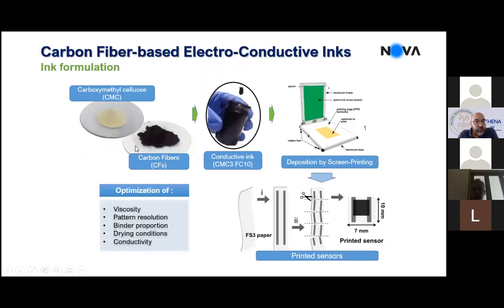And so we made this conductive ink that is a mixture of carbon fibers with a cellulose derivative. So it's a kind of modified cellulose powder. It's called carboxymethyl cellulose, so it's a water soluble powder, and it's good because cellulose is not water soluble, but when you modify it chemically, it may become soluble in water. And so it's good when you want to make inks or upscale this process that you use always water-based systems. And so the idea here was to optimize the ink composition, so to find the right amount of carbon fibers, the right amount of CMC, to get the right viscosity properties in the ink that could be printed.